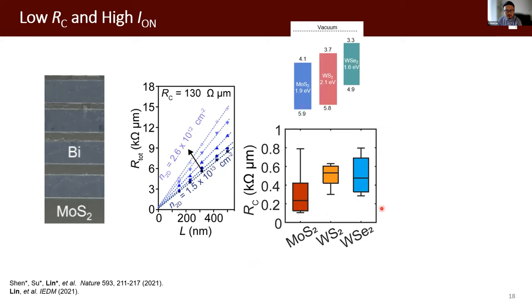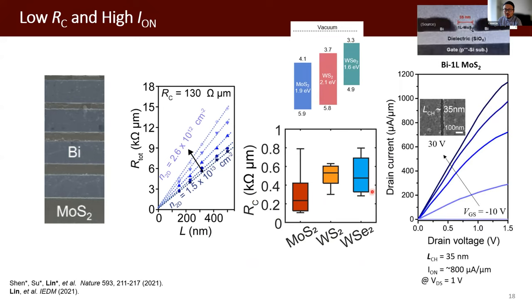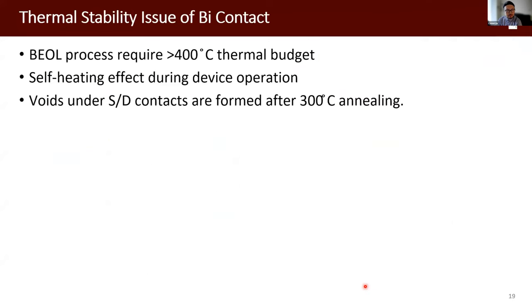And the tungsten selenide has slightly worse contact resistance. This is reasonable because of the different band alignment. We then designed a fabrication approach to demonstrate a short channel length transistor. And we reported the record high on-state current behavior with all these short channel devices.